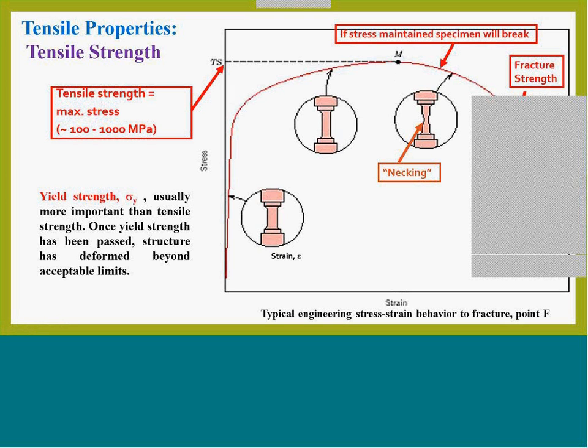So the tensile strength is the stress at the maximum of the stress-strain curve. It happens if the stress is applied and maintained, then fracture will happen. However, at this maximum stress, a neck begins to form at some point, called necking, and fracture ultimately occurs at the neck at this point. Yield strength is usually more important than tensile strength. Once yield strength has been passed, the structure has deformed beyond acceptable limits. If stress is maintained, the specimen will break.